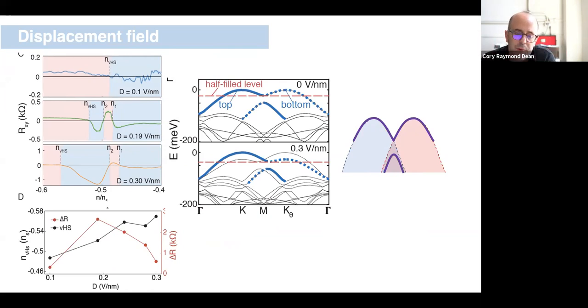Okay, so we can put all this together in a nice correspondence with a theoretical picture. This is band structure calculations done by our collaborators. In particular, what we worked with them to do was to figure out what the band structure of this homobilayer WSe2 looks like, and how it responds to applied displacement fields. What I'm showing here is a band structure calculation that reflects the cartoon picture on the right. The solid blue is the top of the valence band for one layer, and the dashed blue is the top of the valence band for the other layer. This is at zero applied displacement field.